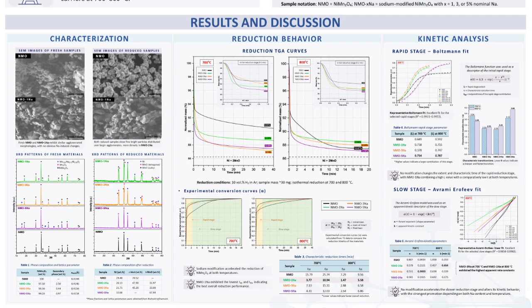A possible explanation for the kinetic enhancement is that sodium modifies the local lattice and defect chemistry of the oxide. Previous studies suggest that sodium can favor oxygen vacancy formation or reduce the energy required for lattice oxygen removal. Easier oxygen removal could therefore accelerate reduction under hydrogen. However, higher sodium contents can also promote sodium-containing secondary phases. These phase changes may partially offset the beneficial effect on oxygen mobility and defect chemistry.